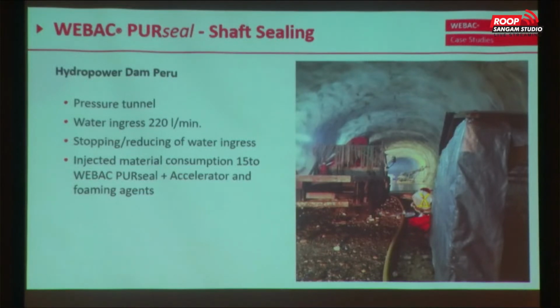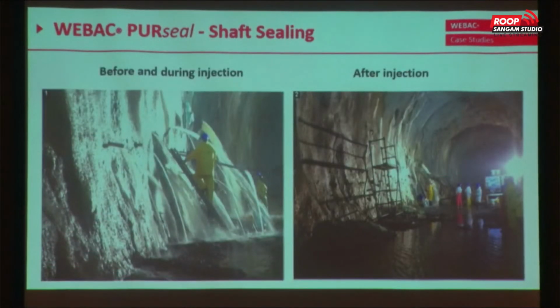Now, that's some circumstances there we faced. And on the left picture, you see we started with the injection, and I'm not sure if you heard about this. For this case, we used also injection lances with inflatable packers. Inflatable packers, that means you push into your borehole, you start pumping the resin, and the packer will be inflated. That will seal the borehole, and after a certain time there's a burst plate. If this is bursting, your resin will be released outside in your borehole or in your anchor, and you start the injection. And on the right side you see we fixed the most problems, but you remember the big water stream there, that wasn't possible on that point.